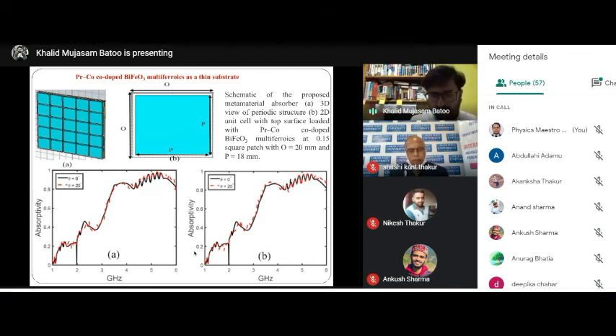Here we changed the angular position from 0 degree to 20 degree, and it showed that the absorption is still consistent. Up to 1 means higher absorption. So up to 6 gigahertz, when we change the frequency from 1 to 6 gigahertz and change the angular position from 0 to 20 degrees, the absorption value is very, very high, almost around 1, meaning 100%. It wasn't fully 100%, it was 96% in our case. So this is one aspect of these ferroelectric or multiferroic materials.